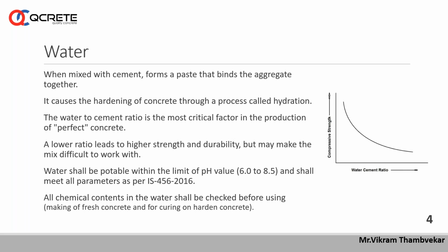Well and bore was close to creek area. So instead of checking all this water quality, they straight away used it, and they found some problem with the concrete at very early age, because the building was under construction. So it is very important to use fresh water and test the water before using directly.